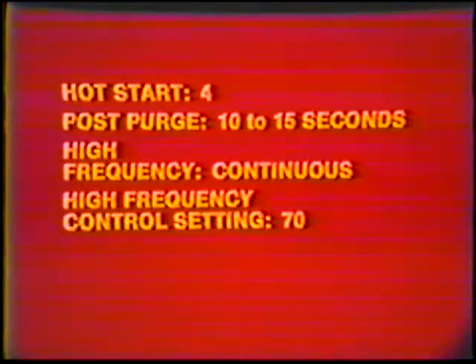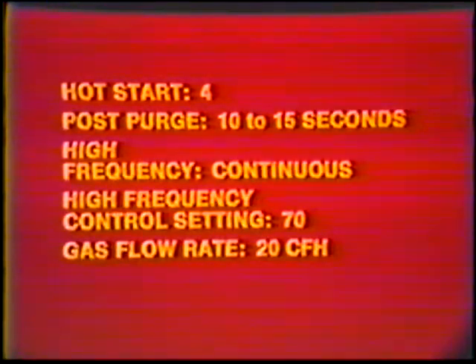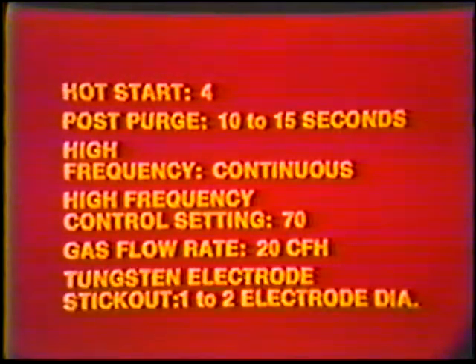The high frequency is continuous, and the control setting is set to 70 to provide a smooth arc. The gas flow rate is again 20 cubic feet per hour, and the tungsten electrode stickout is 1 to 2 electrode diameters.